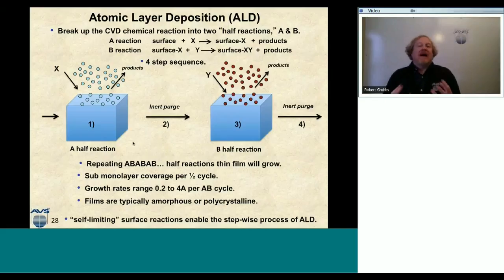Because we bring the reactants in sequentially, now we have these two half reactions of the chemical reaction. So we break this CVD chemical reaction up into two half reactions, typically denoted A and B. And so here's a cartoon of the ALD type process. It's typically a 4-step sequence where I have a surface here, 1, and I bring in X, and X reacts on the surface, and I produce byproducts. Then step 2 would be an inert purge gas where I remove all the X from the reactor, I remove all the products from the reactor, and when that step is complete, I move on to the B reaction where I bring in reactant Y.